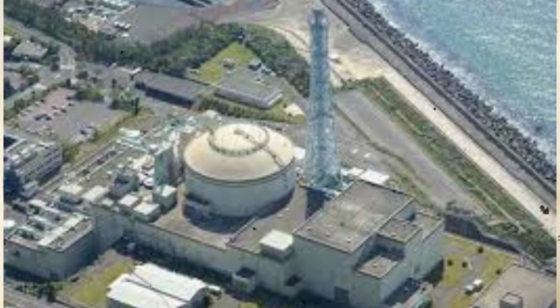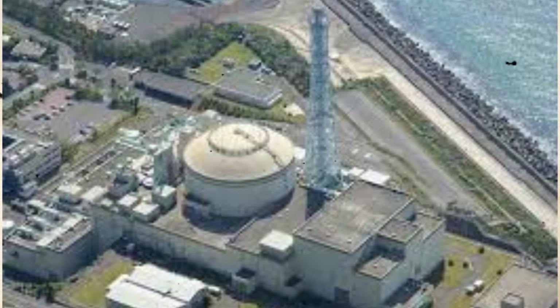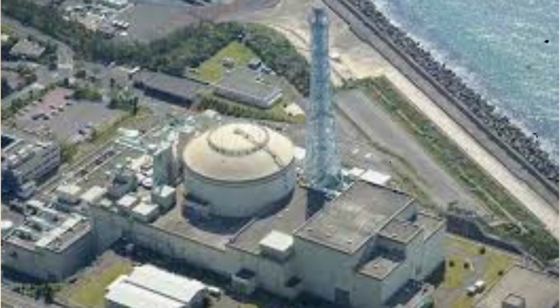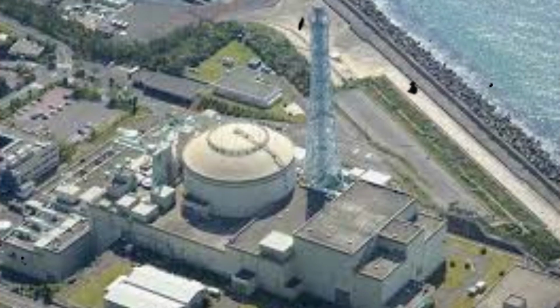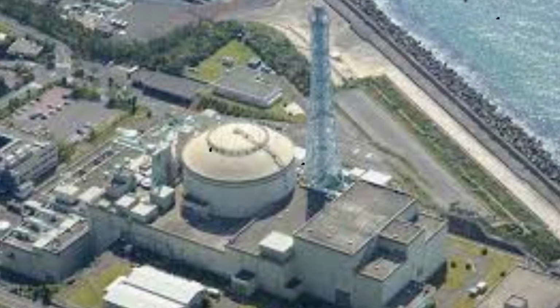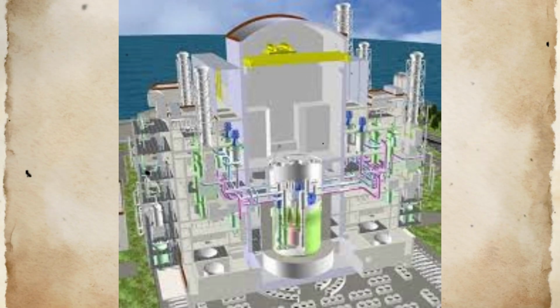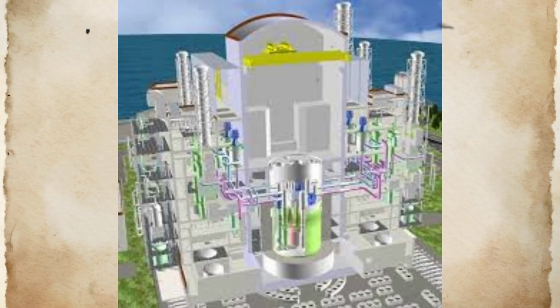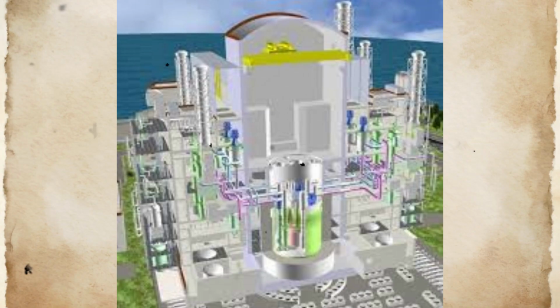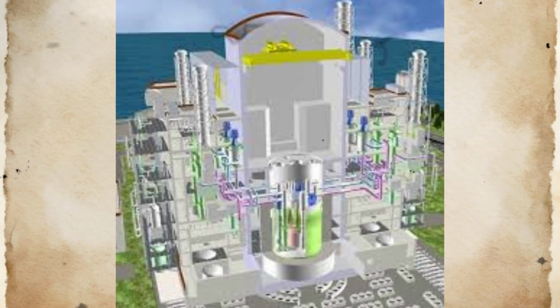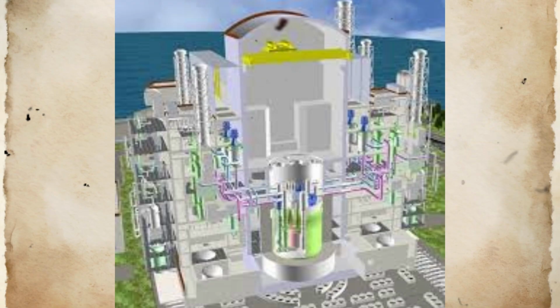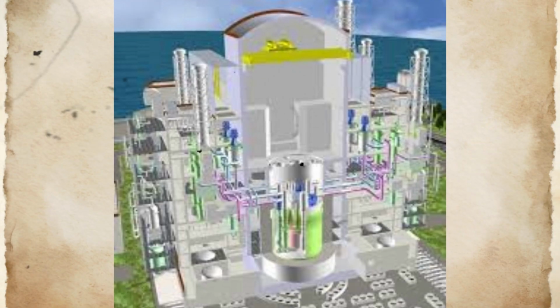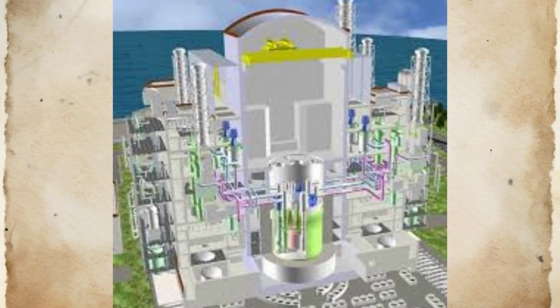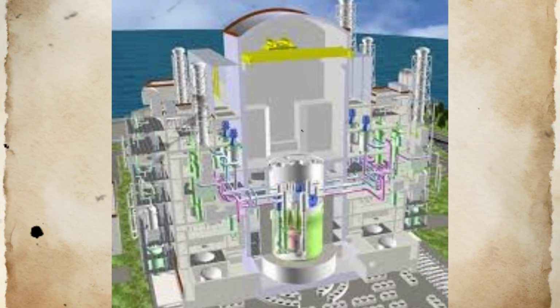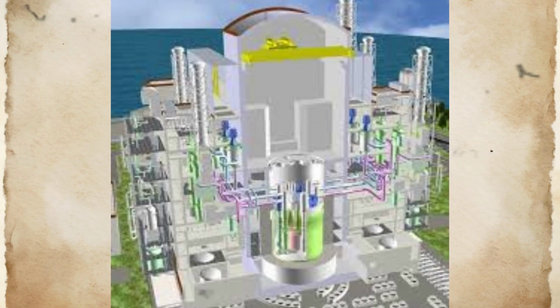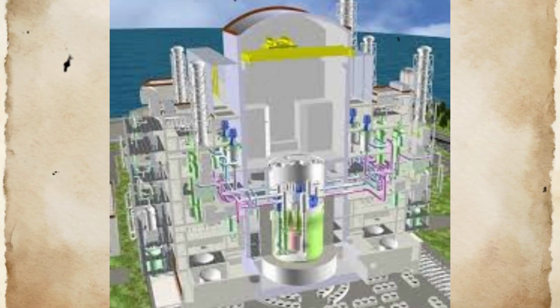The recovery of the lost thermocouple well tip from the distributor at the top of the superheater, on April 24, 1996, provided the critical physical evidence necessary to confirm the failure mechanism that had been theorized during the initial investigation. The separated component, approximately 15 centimeters in length, had traveled through the secondary sodium system following the fracture event, eventually settling in a low-velocity region where flow conditions allowed gravitational settling.